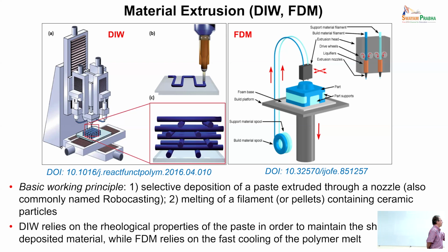In that case, for a polymer, you have a polymeric filament, and then you melt it inside a nozzle, and the nozzle deposits the material, and then the material cools down quickly. And this is very favorable because it means that the molten polymer can retain the shape that it was given by the nozzle. And you can use nozzles that go down to 200 microns in size, and this leads to very smooth surfaces. So this is, of course, again, a layer by layer process. You still have stair-stepping effects, but if the nozzle size is of the order of 200 microns, the surface features are much less evident. So you can really get nicely looking parts for polymers.